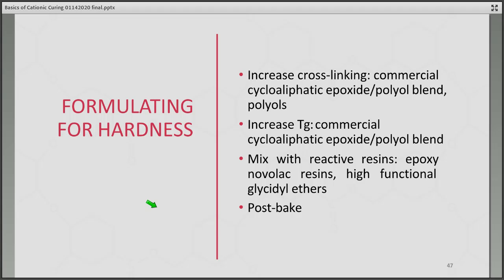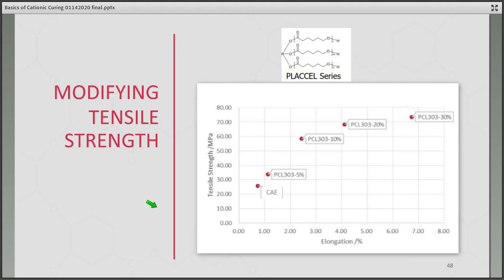If you're going to formulate for hardness, you can increase the cross-linking. So you use some commercial cycloaliphatic epoxide polyol blends that are available from different suppliers. You can increase the Tg of your photopolymer, again, going to a commercial cycloaliphatic epoxide polyol blend that is formulated specifically for increasing hardness or increasing Tg. You can mix in reactive resins such as epoxy novolac resins or high functional glycidyl ethers, and of course your post-bake to further push that reaction, push that photopolymerization, and make a more reactive photopolymer.